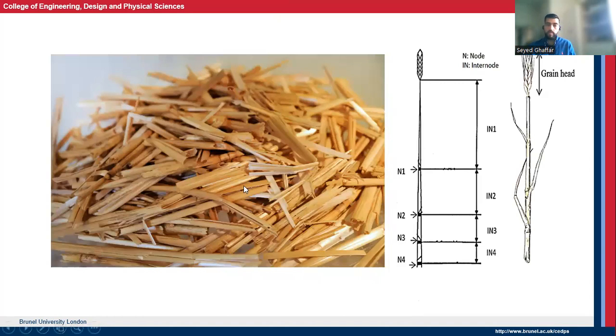And of course, on the surface, we had a lot of wax, a lot of silica, which makes the surface hydrophobic and does not allow any resin to penetrate inside the surface and improve the bonding performance of these raw materials. So we had to remove this silica and these waxes on the surface of straw using an eco-friendly pretreatment.